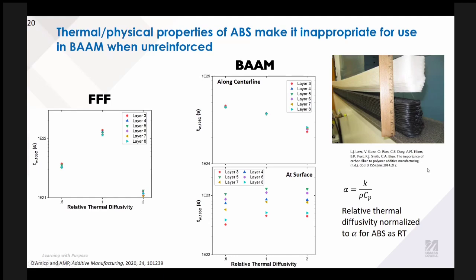And so one of the things we were interested in is whether the chopped carbon fiber is alleviating this warping by changing the heat transfer mechanisms, since the ABS filled with chopped carbon fiber has a thermal diffusivity that's about twice that of ABS, or is the chopped carbon fiber just acting to resist that warping because the chopped carbon fiber adds more stiffness to the material?